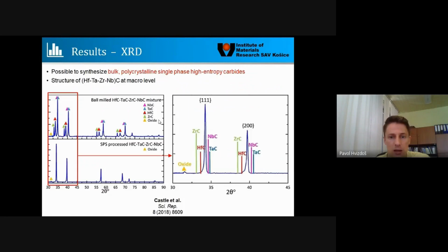So what we got, first of all, the results of XRD showed that the ball milled powder, the mixture, I mean the niobium, tantalum, hafnium, zirconium carbide mixture, contained all the peaks, which means that during ball milling there was just mixing, because it was a relatively low speed milling, not mechanochemistry, the original phases were detected. So it means the powders were mixed, but there was no basic chemical reaction between them.